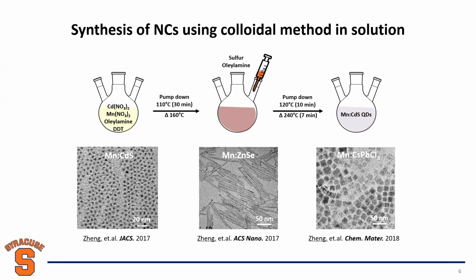Okay, the reaction is very simple. You can see the final product, manganese-doped cadmium sulfide quantum dots, has three elements in the product. We use manganese nitrate as a precursor for manganese. For cadmium, we use cadmium nitrate. In an organic solvent at high temperature, we inject the sulfur solution, which is in an organic solvent as well. If you don't let the reaction go too long, too hard, you can make nanoparticles. Actually, it's very simple. My undergrad students can make nanoparticles in my group. So you can see this is a TEM image of manganese-doped cadmium sulfide quantum dots. Okay, spherical particles.